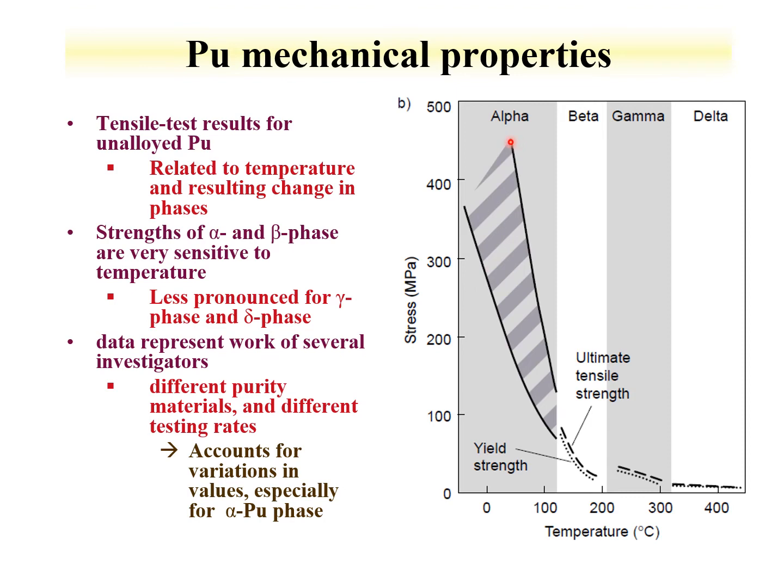But what we do see, and what's consistent, is this large change in stress as a function of temperature. Over 100 degrees, we go from something on the order of 100 to 400 megapascal, whereas for the gamma and delta phases, over 100 degrees for the delta phase, we hardly get any stress change.